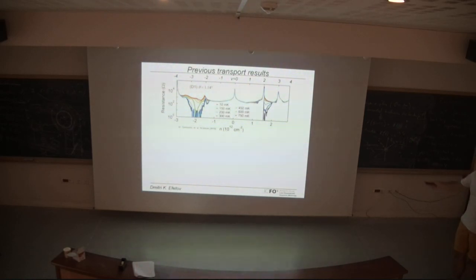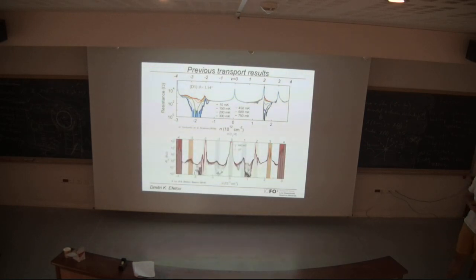In my group, we basically tried to repeat these experiments, and we had a specific focus on making devices cleaner and cleaner. So this is now data from devices of our group. As you can see, at first glance, it looks similar to this. All the scales here are the same. Starting at the band insulator on the hole side here, we get band insulators. We also get a band insulator on the electron side. We get a Dirac peak in the center. And we also get the insulating states at -2 and +2.